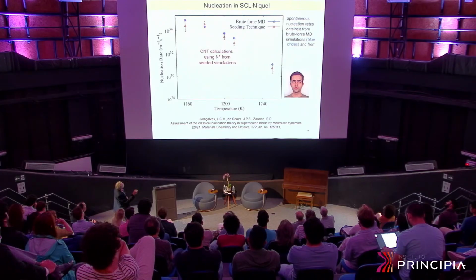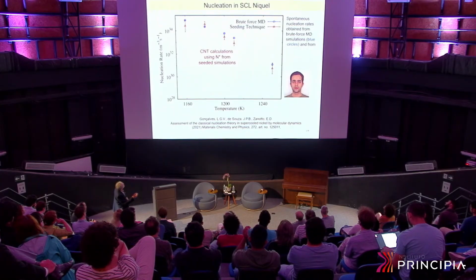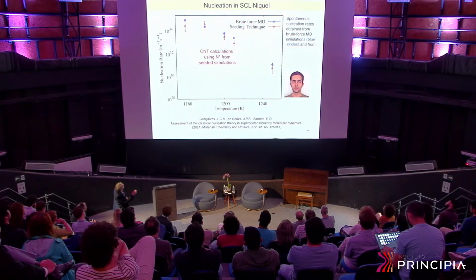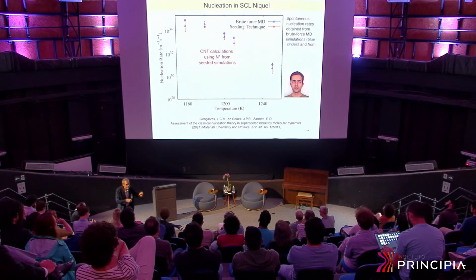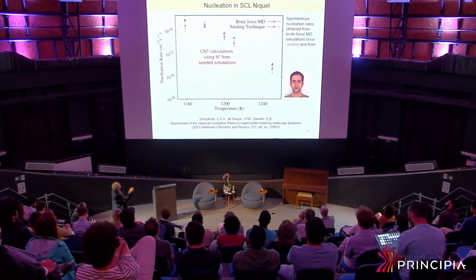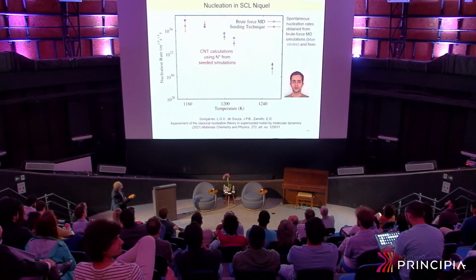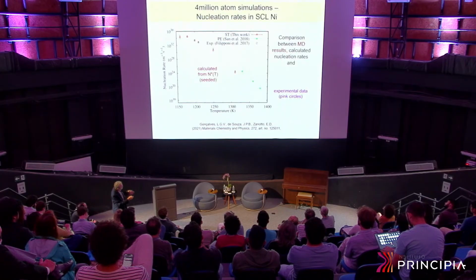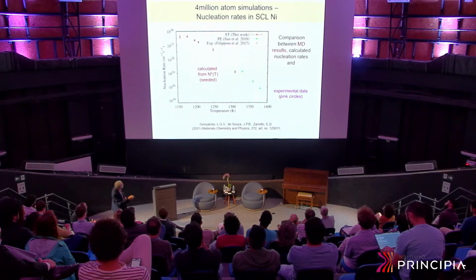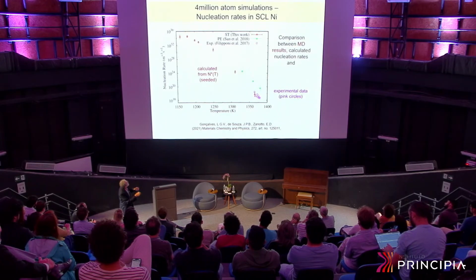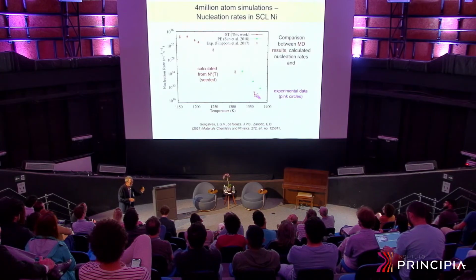So these are our MD simulations, brute force MD simulation, spontaneous nucleation, the blue circles, then calculations from CNT using the seeding technique to get the interfacial energy. These are all calculations, very nice agreement. And finally, people had measured here. Measurements and our data here. Very nice agreement. We cannot measure it here, but these are extrapolations using the parameters derived from MD simulation plugged in the classical nucleation theory.